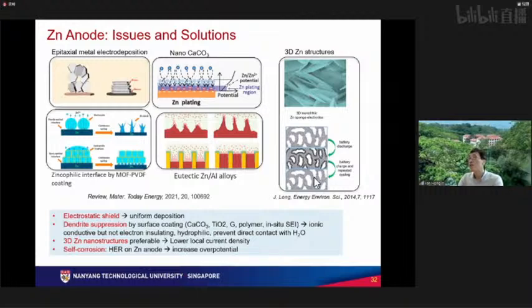So that's why actually a lot of work, if you do not want to make a dendrite issue, then you go to three-dimensional zinc. But if you really want to make a storage device out of zinc, then you go to a zinc foil, right? But interestingly, if you look at all this work, people try to coat the surface to increase the hydrophilicity, make the surface wettable by water, right? So all the different mechanisms are summarized here.